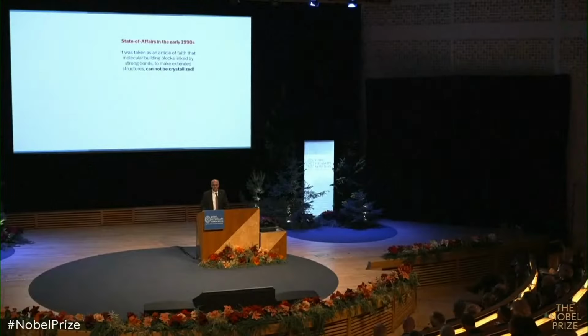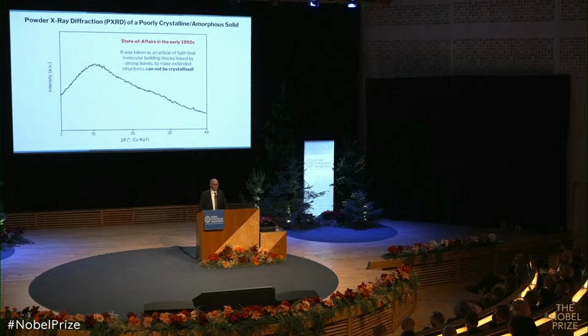Well, that sounds easy enough. But when you have strong bonds, something very bad happens in the lab. And that is, you make ill-defined materials, not like those beautiful crystals that were described earlier. This hump indicates that your material is completely disordered. The homogeneous pores that I was talking about, if they're present, they wouldn't be homogeneous. The framework that I was talking about that should be robust, it wouldn't be. This thing is a complete mess, and it's the antithesis of what a chemist wants to do.